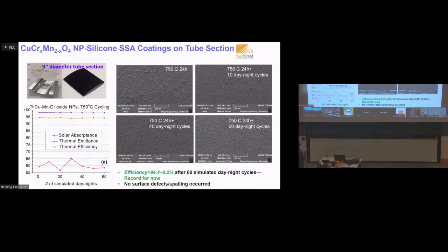Okay, so here's the endurance testing. We also coat on curved substrates and measure. This is basically an attachment that Tsang designed. You can flip this piece over so that the curvature perfectly matches that one. You can put it on the spectrometer so that you don't get any stray light in the measurement.